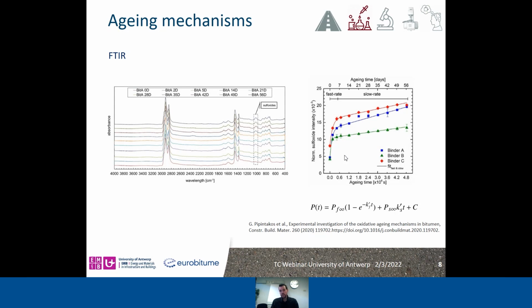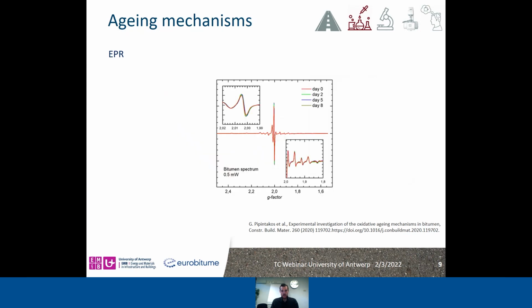And this supports indeed that from FTIR we can separate the fast and the slow rate phase. However, as I mentioned in the beginning, it is believed that from the fast rate phase there is a different chemical path that also creates radicals, organic radicals. For that, we used, as I mentioned, an EPR, and from the spectra, as you can see, over time, we were able to isolate organic carbon-centered radicals, and secondly, different metal species, in this case, vanadium ions.